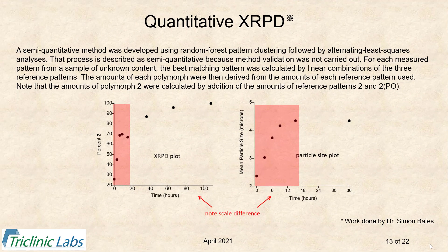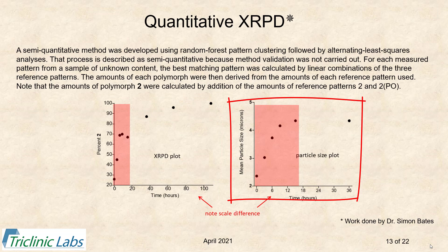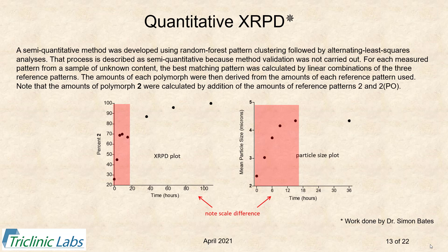The full pattern X-ray method was used to process data collected from the 40-degree C interconversion experiment. The resulting data plotted on the left-hand plot, alongside the particle size plot shown earlier, with shaded areas representing equivalent time spans across the different x-axis scales. We were able to follow the conversion well with X-ray, showing conversion occurring in around 10 to 20 hours—consistent with the particle size plot. That X-ray method was used to aid drug product development: first by adding an aging period to allow the change to occur, and ultimately by simply using polymorph two from the start. Polymorph one results from methyl ethyl ketone crystallization and polymorph two from alcohol crystallization.